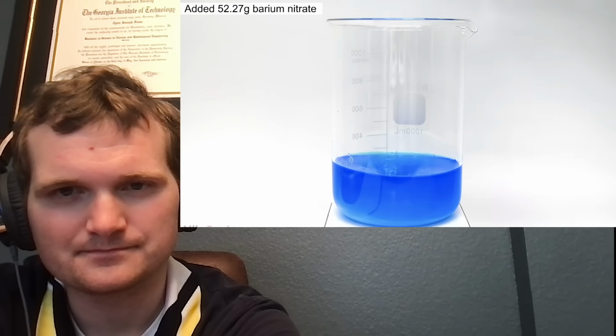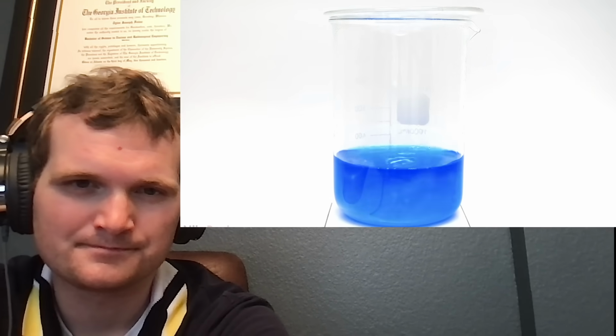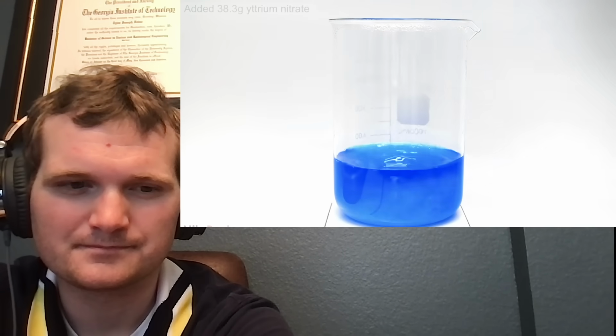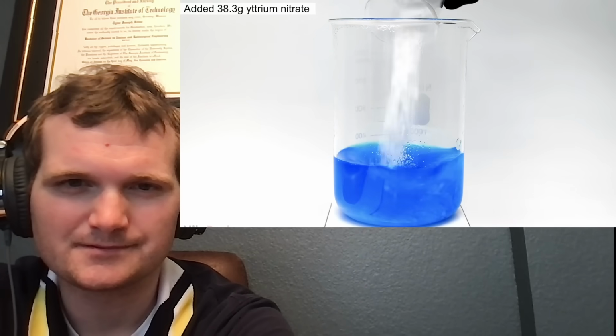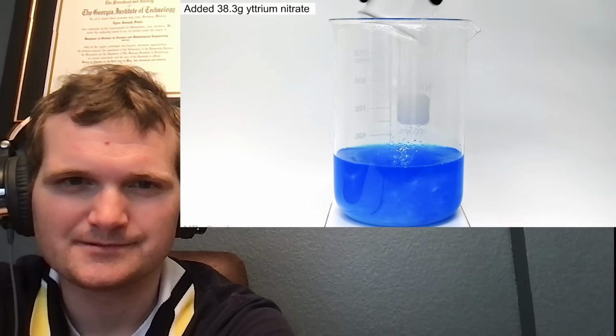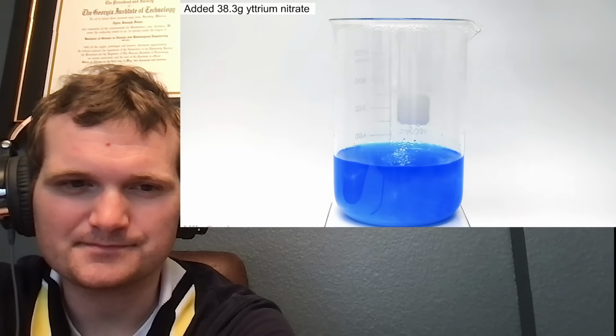This caused it to all quickly clear up, and the next thing that I added was 52.27 grams of the barium nitrate. This, however, really wasn't very soluble, and I had to heat it a bit with the hot plate. I let it stir for about 20 minutes, and it had gotten quite hot, but there was still a decent amount of solid stuff. This was fine though, and I just went ahead and added 38.3 grams of the yttrium nitrate that I had just made.